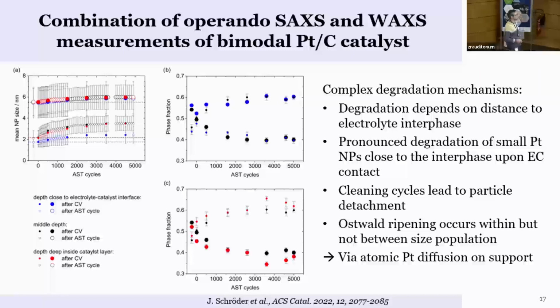What we then came up with as a conclusion is that you have a pronounced degradation of the small particles close to the interface. They are particularly vulnerable to degradation. So the Ostwald ripening mainly occurs not between the size populations, but on one carbon support. So basically we couldn't identify any small particles from the one catalyst ending up on the other, at least in our data, that was not in there. And so most likely it's more an atomic diffusion on the support, but not ions that from the small population end up on the larger particles.